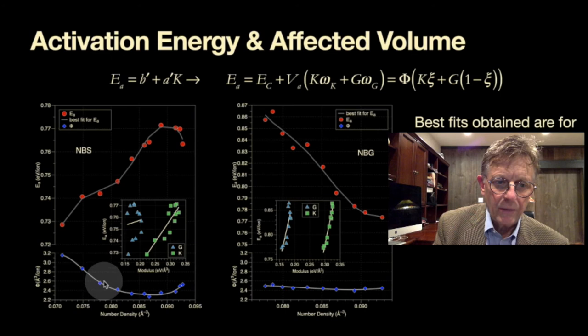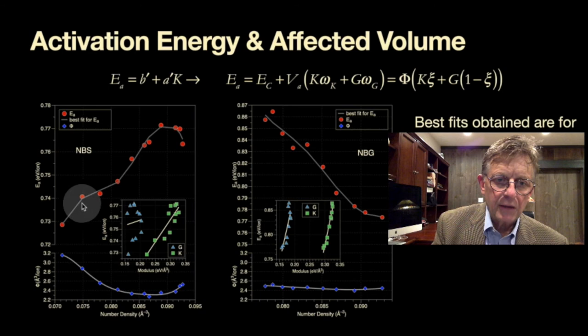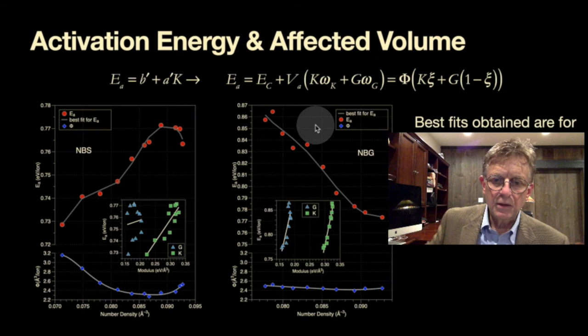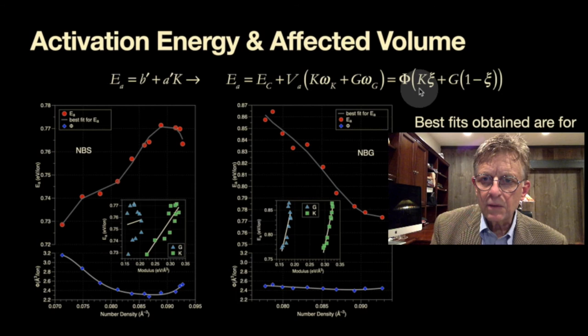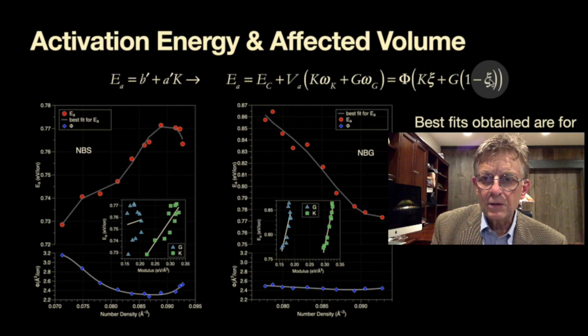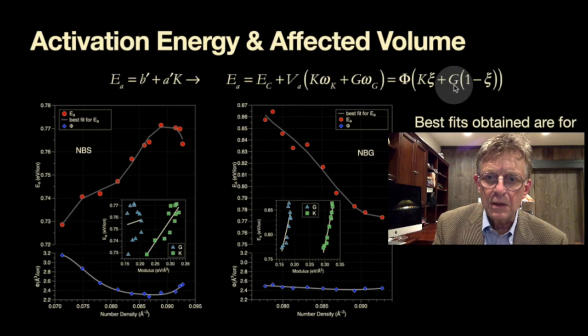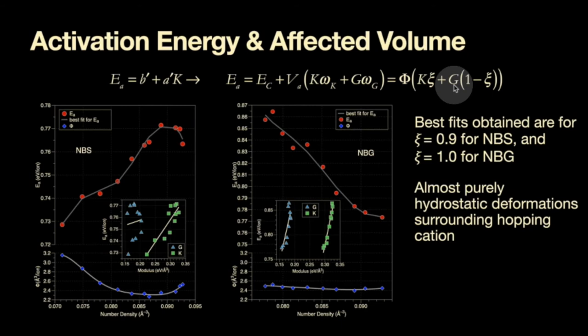So this expression now is being rewritten into the expression on the right and we have this might be the B prime but then we have the A prime is some kind of a factor of xi and capital Phi. And what we do now is we take, we do a double fit, a simultaneous fit of two data sets. One of them is the measured activation energy using this expression but at the same time we have the unknown factors xi and also the affected volume in here and we require that those would be a continuous function, that means that the data would not erratically vary. And so by making that constraint we are able to fit two sets of data. You see the affected volume or this factor capital Phi is down here and then the activation energy is up there for both the silicates and the germanates. We get a decent fit and so these two fits are interdependent.